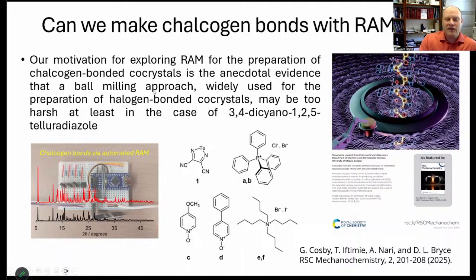So what is our motivation? As I've explained here, both in our lab and from hearing from other people, when trying to use a ball mill on these types of donor molecules, we found that the ball milling was too harsh, meaning that we'd get decomposition of that molecule even when trying to use gentle grinding conditions. And it was just not a good route to get these cocrystals. So we thought, well, RAM might be less harsh. Maybe we can do something here and find a new way to make known and novel cocrystals without solvent. At the same time, in this paper, we built a little tool to help with automating some of our RAM experiments, which I'll touch on briefly.